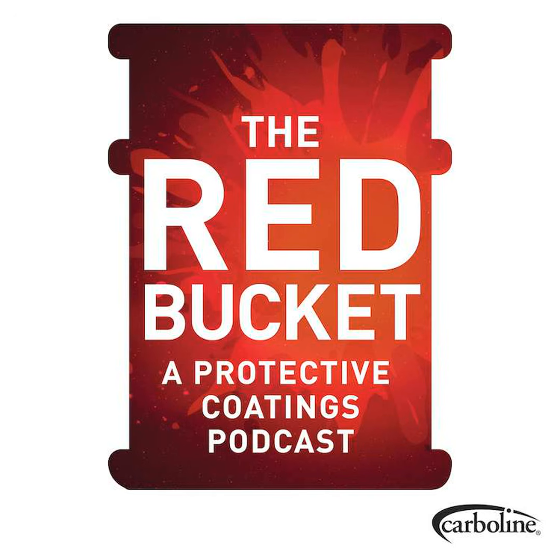And now top coat. You want a top coat for a variety of different things. Acrylics typically don't require a top coat because they are UV resistant. Our epoxy is a modified epoxy, so it does not chalk as aggressively as a standard epoxy, but it will eventually chalk. So if you want your tank to look good 5-10 years from the application, you'll want to top coat it for UV degradation. You also might want to top coat it if you are downwind of a cooling tower that might get constant moisture on the system, cause possible mold growth, or have chemicals in it as well. So chemical resistance and weathering resistance are the two main reasons that you'd want to consider a top coat.